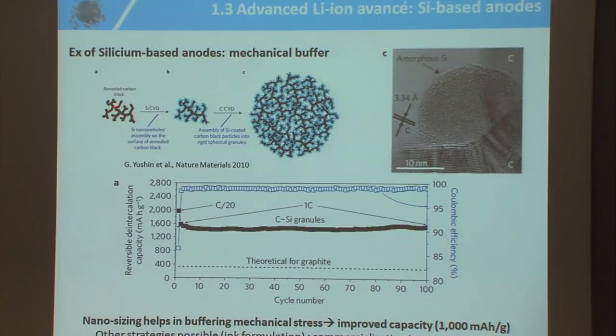And you have here a strategy. You start from porous carbon. You do a CVD of silicon onto it. And then here you have this 10-micron particle decorated with silicon. You have here amorphous silicon, and this is graphite, a TEM image, graphite layers. You can see that this is graphite, 0.33 nanometer between the graphene layers. And you have here, more or less, 15 nanometers size silicon particle.